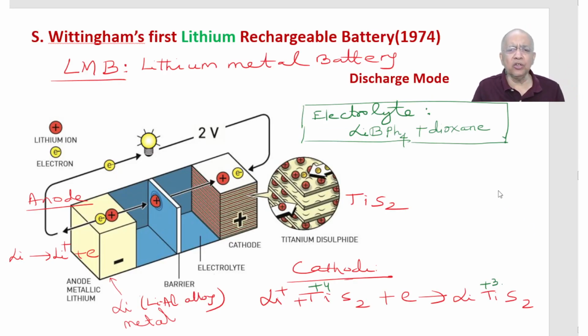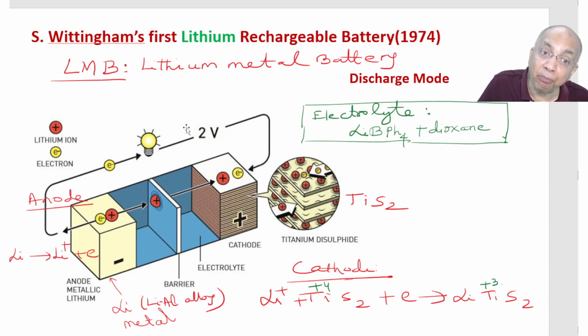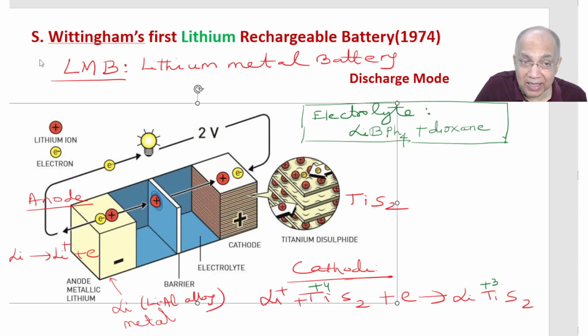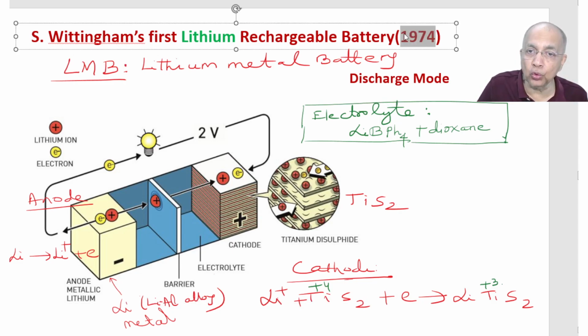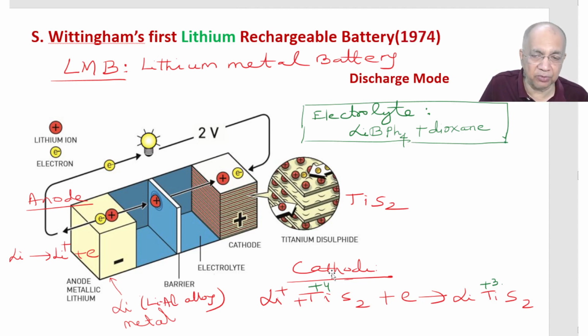Is it not interesting? Now let me tell you in a nutshell the historical development of the lithium battery. In the beginning it was not a lithium ion battery but a lithium metal battery, LMB, where lithium metal was used. I have already explained Whittingham. M. S. Whittingham was the first person, in 1974, who developed a lightweight rechargeable lithium metal battery. I have already told you, he used titanium disulfide as the cathode material, with the same parallel structures where lithium ion gets intercalated, and titanium was going from +4 to +3 in the similar manner as we found for cobalt in the discharge reaction. It was giving a 2-volt battery, so it was of lower capacity at that time. Lithium metal was used as the anode material, sometimes lithium aluminum alloy.